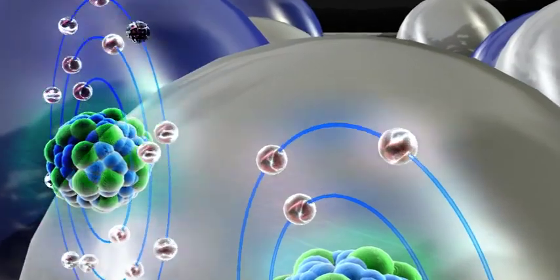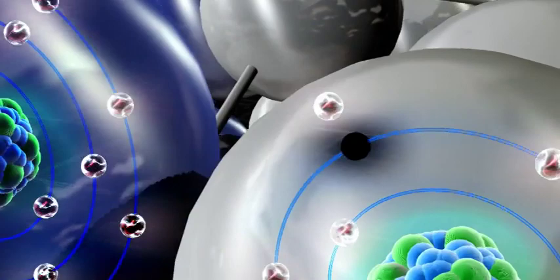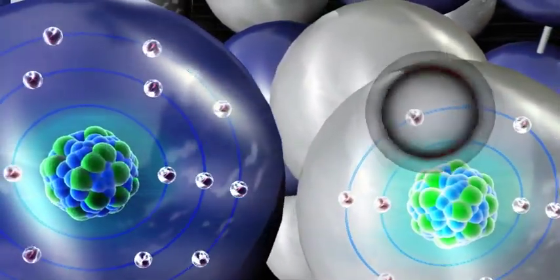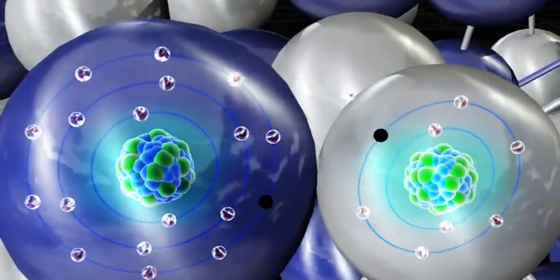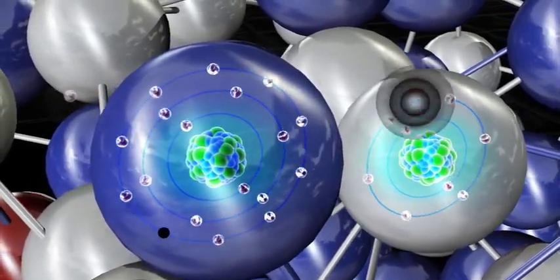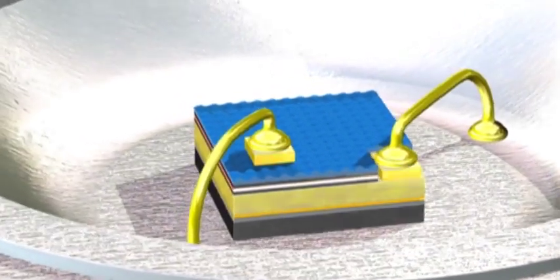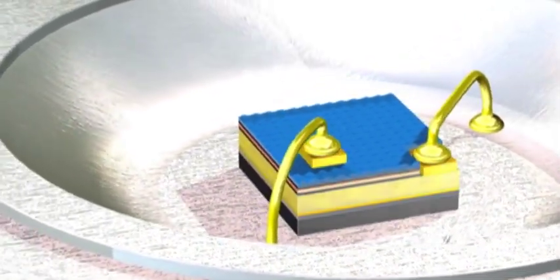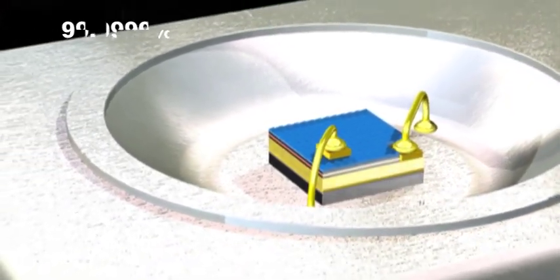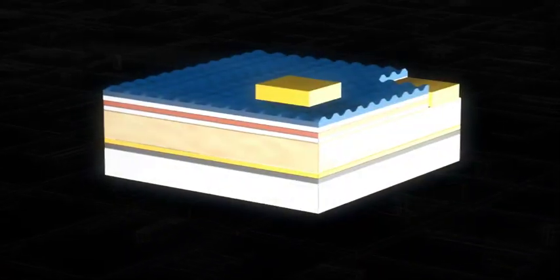We also encountered substantial losses associated with non-radiative recombination. Imperfections in the crystal growth create non-radiative current paths that generate waste heat. OPTEK mitigates non-radiative recombination through advanced proprietary metal-organic chemical vapor deposition system design and crystal growth sequence. Perhaps most important, OPTEK uses what is called the six nines in specifying its chip chemistry. OPTEK will typically use compounds at 99.9999% purity, an expensive proposition.